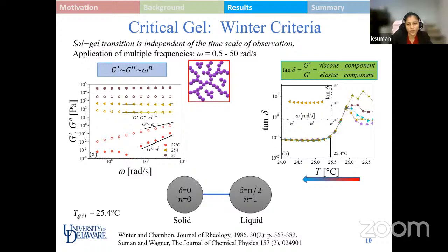So the depletion system is quite different from the system which I'm studying, which is the adhesive hard spheres. So let me first state that the phenomenon reported in the first part of the work, which is the sudden change in modulus value, is not a universal thing. It's very specific to this system. Obviously, it happens at different concentration, but it is not something which is usually seen for any polymeric or any colloidal system. So we tried it for different polymer system standard solution. Obviously, we get a very slow continuous increase in the modulus value, and this interesting behavior is very specific to this system.